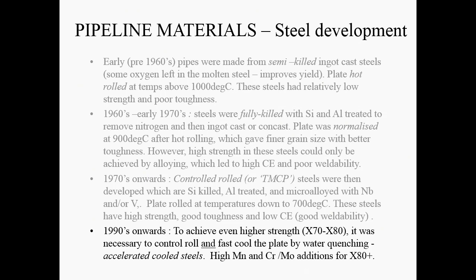So, from the 1990s, to get the high strength steels, that's X70, X80 and higher grades, we needed to controlled roll and fast cool the plate by water quenching. So these are sometimes called accelerated cooled steels. Basically, if you leave a steel at temperatures of 500 or 600 or 700 degrees C, there is a tendency to try and increase the size of the grains. Grains have surface energy, and if the grain size is very small, there's a lot of surface energy in the material, and you can minimize it by increasing the size of the grains.